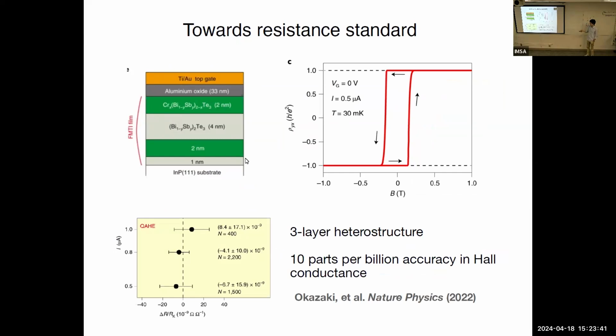This group in 2022 was able to grow a sample of magnetic TI which shows a Hall resistivity accurate to 10 parts per billion. So it's, I think, one order of magnitude lower than the current standard set by graphene. But in graphene you have to apply a magnetic field, and in this case you just need, I think, 0.1 Tesla. You can do it even with a permanent magnet, which only supplies a very small amount. So this makes it very practical. And I think in the near future they will actually meet the resistance standards, and you can measure ohms and everything with just what you measure from these magnetic TIs.